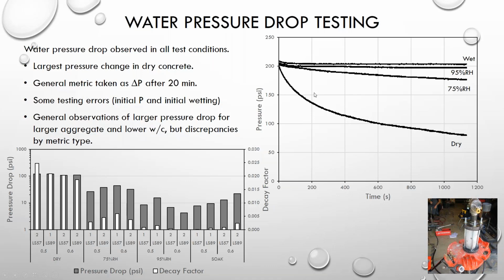And so one metric to do this is actually to measure a delta in pressure between the initial time and 20 minutes, for example. This 20 minutes was chosen fairly arbitrarily, but we see that there can be consistency as long as the test was made similarly. But we also try to fit these graphs. We see that they follow an exponential decay, and we can get a term that describes the whole entire line. So it resolves some of the discrepancies you may get by having differences in the early initial pressures and the timing that you choose for the timing of the pressure drop.